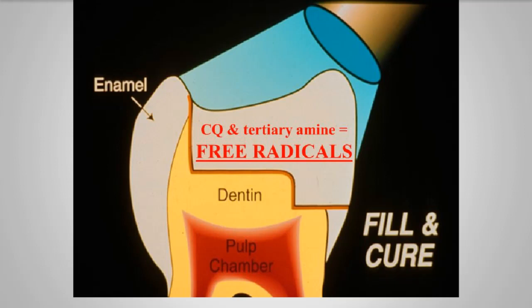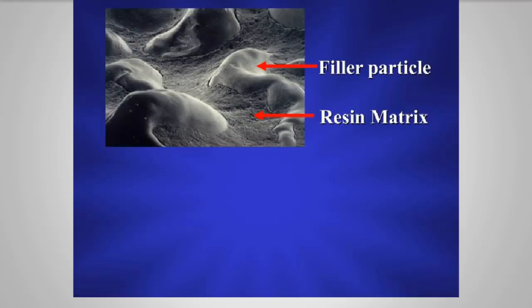Now here we have a scanning electron microscope graph of a polymerized composite. We can actually see these filler particles here essentially surrounded, if you will, and encapsulated by a sea of polymerized resin. And these filler particles are typically silanated. Silane is a coupling agent between inorganics, which are the filler particles, and organics, the resin matrix.